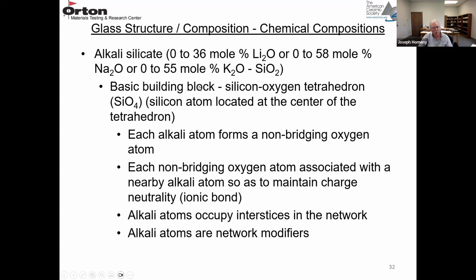The basic building block is still the silicon oxygen tetrahedron, the SiO4 unit, with the silicon atom located at the center of this tetrahedron. Now, when you add an alkali atom, it forms a non-bridging oxygen atom. So each non-bridging oxygen atom is associated with a nearby alkali atom, and that maintains the charge balance. It has to be electrically neutral, an ionic bond. These alkali atoms are going to occupy the interstices, or these open spaces in the network.